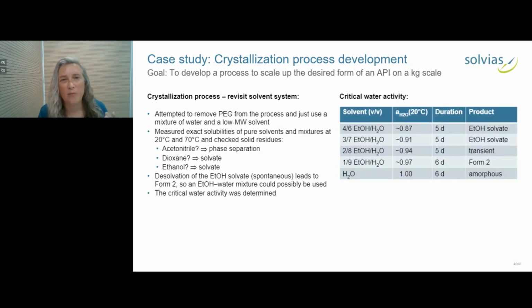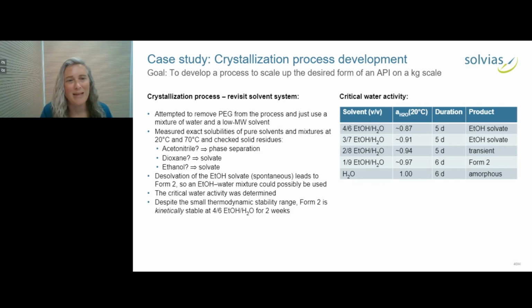The next step then was to determine the critical water activity. In this table on the right, we looked at different ethanol water mixtures with different water activities, and we equilibrated the ethanol solvate and form 2 for 5 days to see what form it converted to. Again, thermodynamically, if you're not exactly at the critical water activity, there will be one form. What we saw was the ethanol solvate was stable up to very high water activities, and there was only a very small range where form 2 was thermodynamically stable.